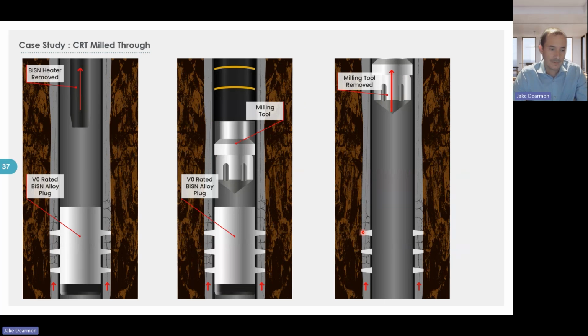We remove the heater, and then from a P&A perspective, we could leave the plug like this, which we did on some wells, or in other wells where we needed access all the way back down, we go in with a special BiSN mill that's alloy friendly, and we actually mill this back out to the full bore, so you're not handicapped by a restriction like you would get with a patch or something afterwards. So it was a mixture of wells on this particular campaign. Some that we milled through, some that we didn't.